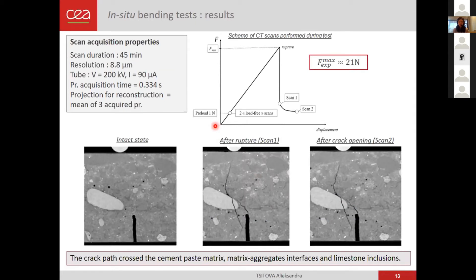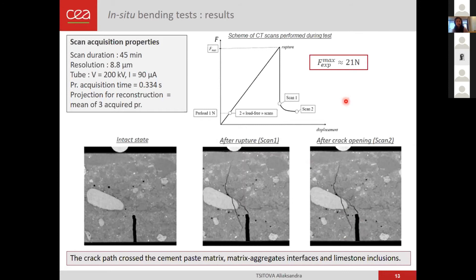With this experimental setup and specimen geometry, we could not achieve a test with steady crack propagation. The rupture was always brittle, and after cracking, the crack propagated instantly across the whole height. During testing, first two scans were acquired with a small preload to capture the intact state of the specimen. Then the specimen was continuously loaded until rupture, and after rupture the next scan was acquired. A small increment of displacement was applied for crack opening, and then the final scan was acquired. The data from the test include scans in intact and ruptured states, the rupture force, and observation that the crack passes through the cement-based matrix, through interfaces between aggregates and the matrix, and apparently through the limestone particles, which are brittle.